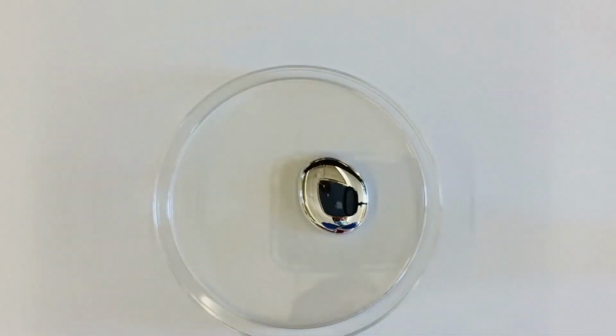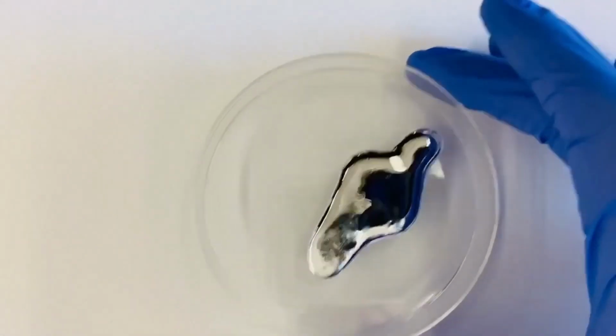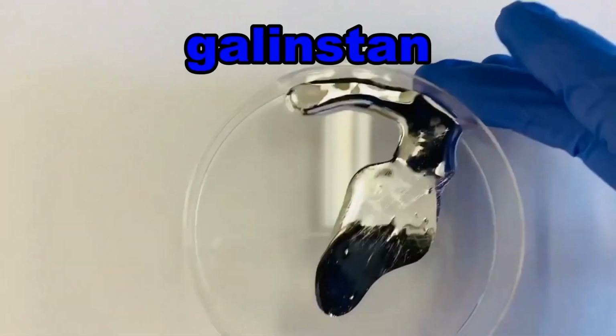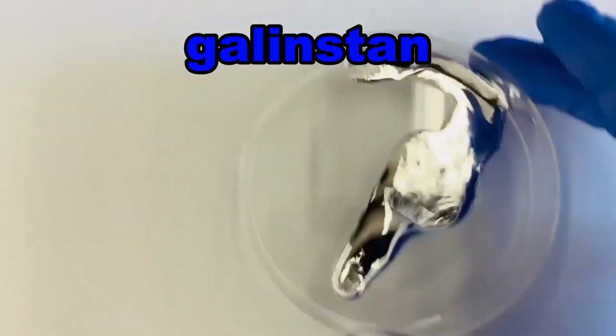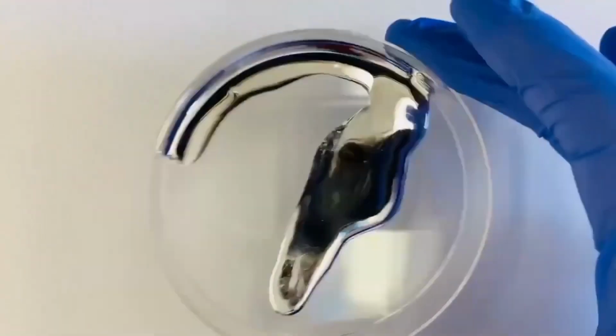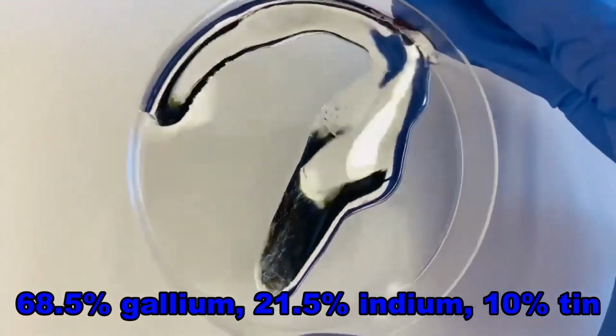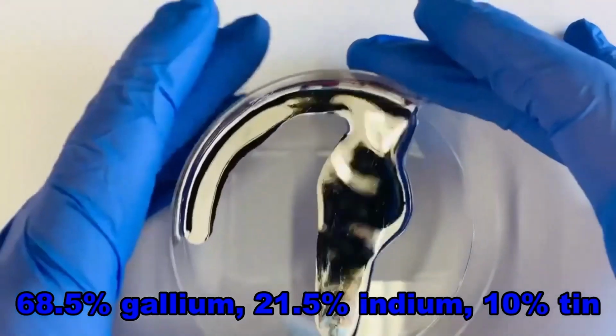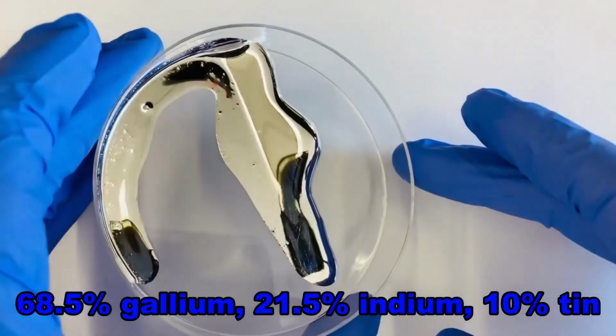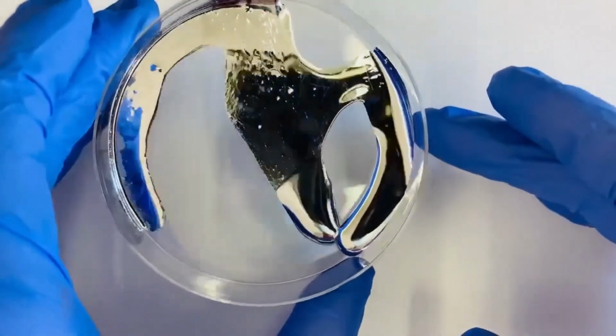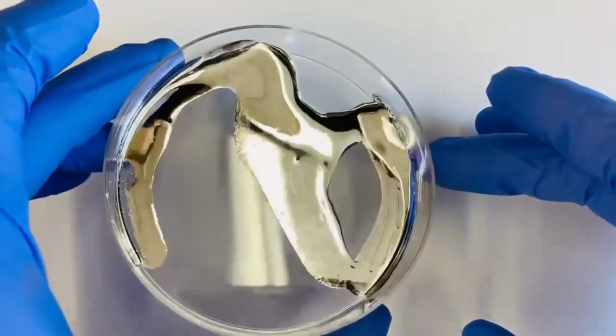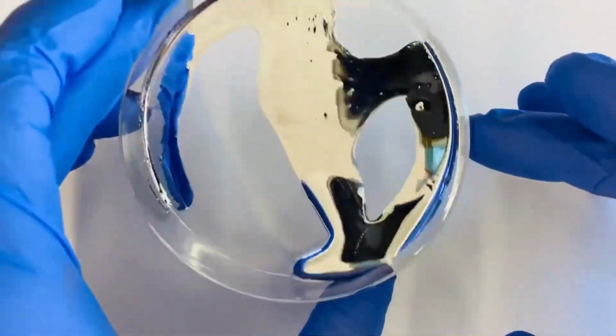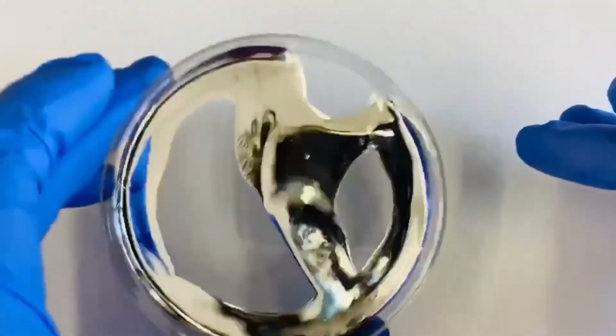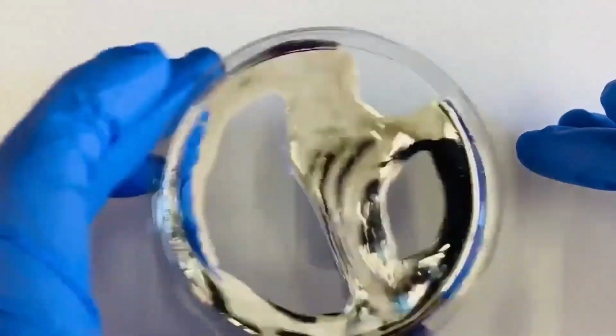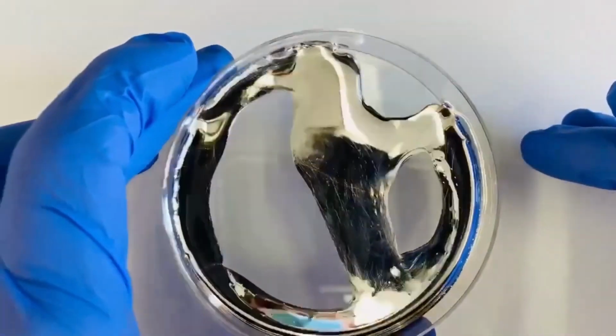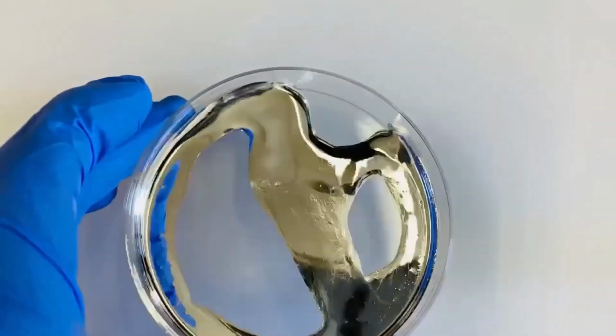Galinstan features a melting point of negative 19 degrees Celsius, but retains its composition until a boiling point of 1300 degrees Celsius, only marginally less than the melting point of most steels. While in liquid form, Galinstan takes on a glossy silver appearance, consistent with the liquid form of the Terminator. This property allows Galinstan to be painted on surfaces, such as glass, in order to make mirrors. It also enables Galinstan to be a non-toxic replacement for mercury in thermometers.